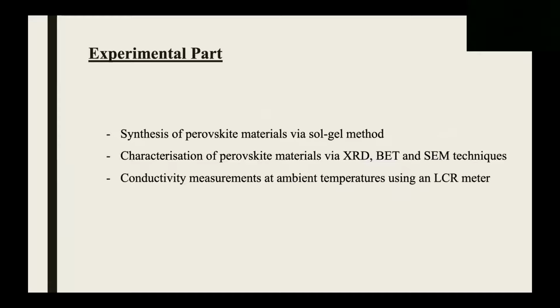In our study, we have prepared perovskite materials via modified sol gel method. And we have analyzed the crystal phases of each electrocatalyst sample via X-ray diffractometer. And also we have determined the specific surface area using the BET technique. And also the microstructure of each electrocatalyst sample was determined using a scanning electron microscopy. And after the preparation procedure, the electrical conductivities of the electrocatalyst samples were measured using an LCR meter, and it happened, like I told before, at the room temperature.